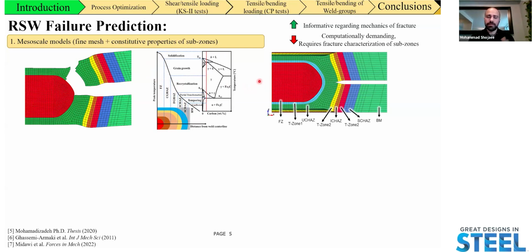So adoption of these types of models, the mesoscopic models, is really going to be informative in terms of the mechanics of fractures. So things such as the crack initiation region and crack propagation path are going to be modeled very accurately in such models. But on the downside, since these models are using really small element sizes, they're going to be very computationally demanding, and it requires a lot of fracture characterization for different subzones, which can be challenging.